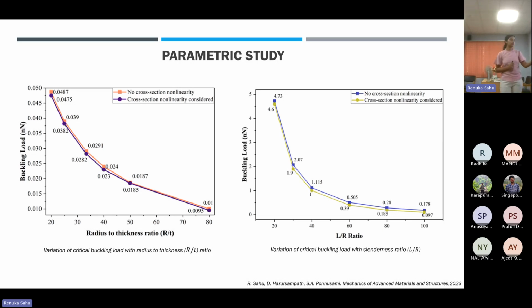We also did variation of critical buckling load with slenderness ratio, keeping the radius of the CNT constant. The difference between the cross-sectional nonlinear and no cross-sectional nonlinear case is quite evident, and for higher L/R ratio, meaning a higher length of CNT, there is much more difference between the two cases.